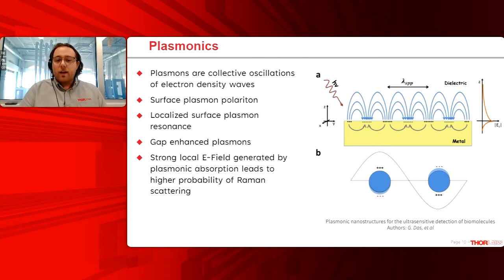Another type of plasmon that you can excite or generate is a localized surface plasmon resonance. This is when you have a metallic nanoparticle, and again, with some careful engineering and design, you can very efficiently couple light to these nanoparticles. Now, when plasmons are oscillating inside of a nanoparticle, they're confined to this very localized area. And therefore, you can see some electric field start to leak outside of the particles.